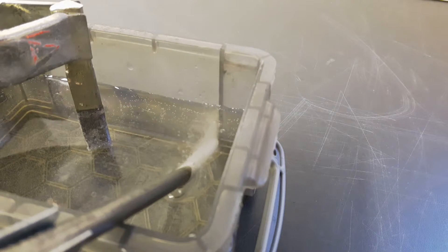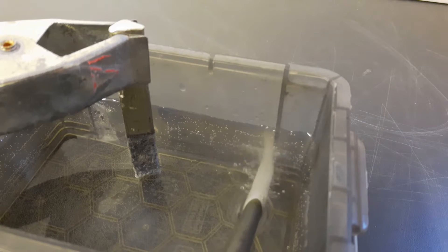Five minutes later and I am frustrated. Of course it is actually electrorefining tin — exactly what I thought would happen. The table seemed to be correct: 100 millivolts of difference does prevent me from creating stannous chloride solution. But no matter — I always wanted to purify this tin anyway. So the only thing happening is that I'm separating the tin from the copper in this alloy, and we will be left with approximately 99% tin. That's a good deal.